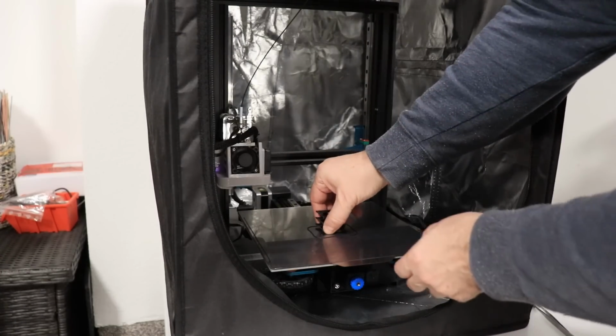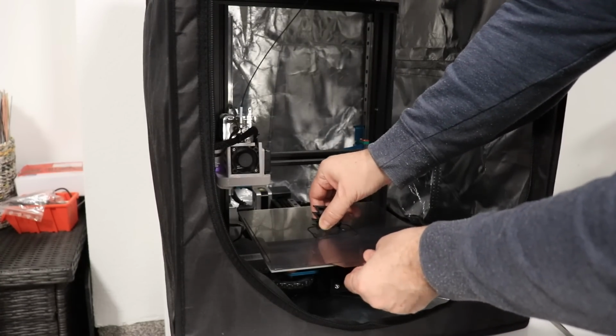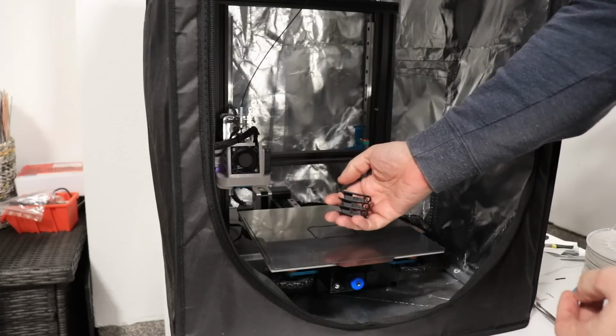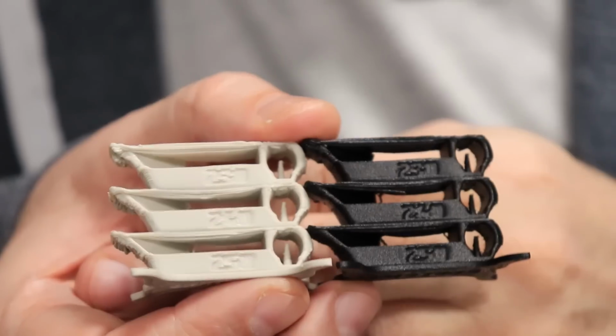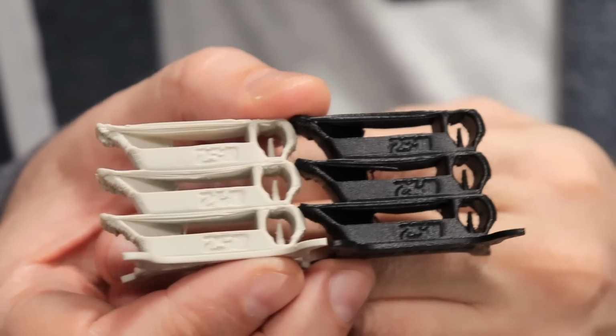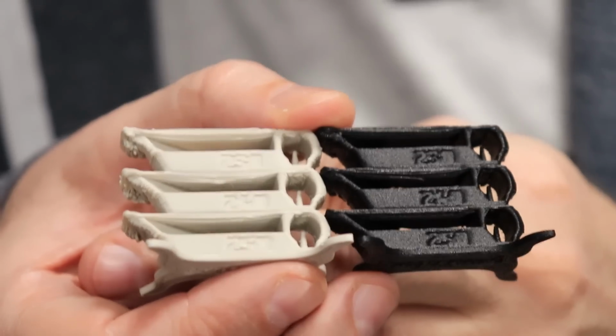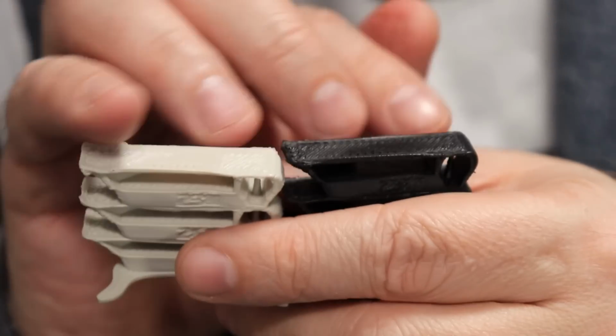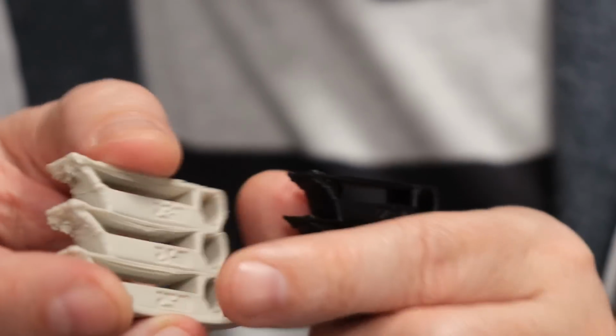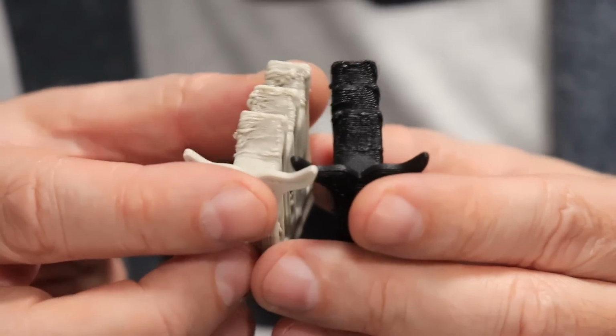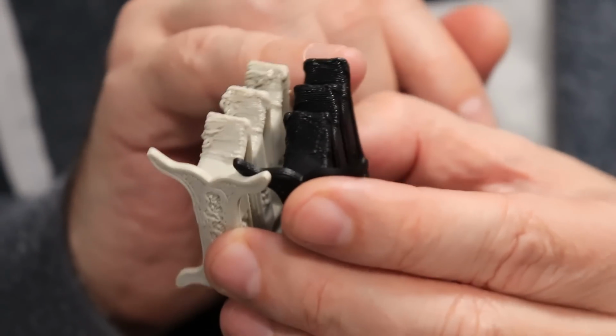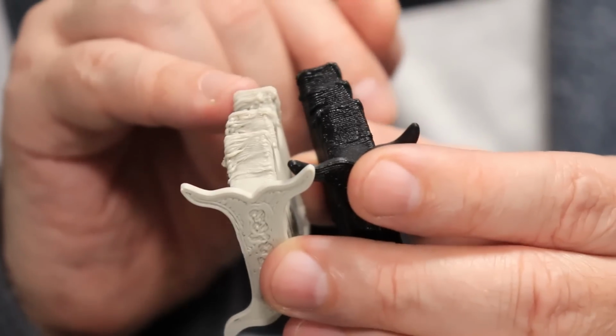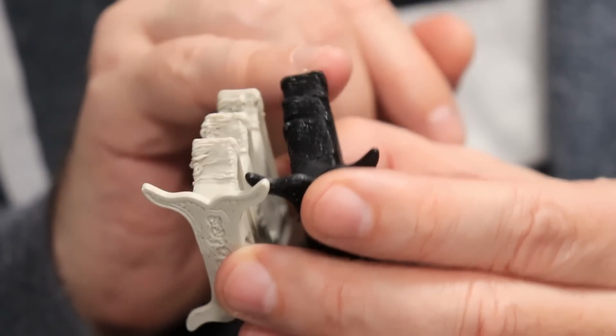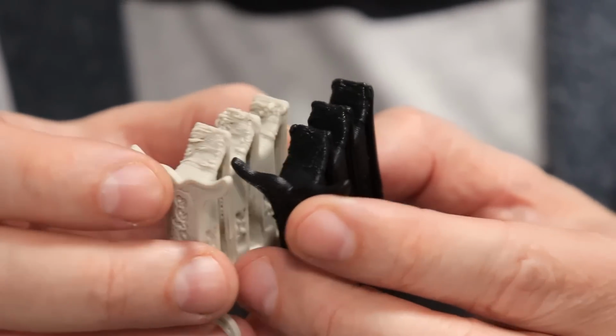The bed cooled down. And side by side these two temperature towers look very similar from the aspect of the stringing or the bridging. The top surface is also over melted in both cases, but the biggest difference we can see in overhangs. So this version with carbon fibers looks better compared to the regular ASA, but this is also far from perfect, so definitely some minimal part cooling is required here.